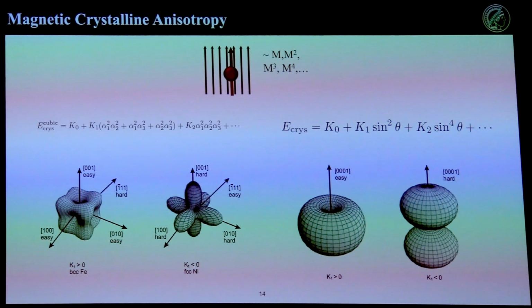And you can already see how this can help to stabilize magnetic textures, because now you can say, hey, I can point my spins on any of these axes with a low amount of energy. Then you have this nickel case, where the easy axis is along the 1, 1, 1. So you can see how these have very different things. For the hexagonal cases, in the simplest form, it's much more complicated in these examples, so you have to go to a couple more terms here, but you usually have either an easy axis or an easy plane and a hard axis. And it just depends on the signs of these things.